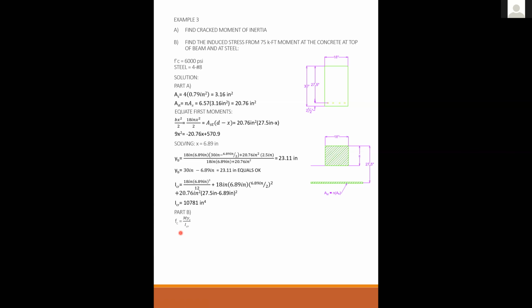So f sub c, the stress in the concrete at the top of the beam, is My over I. So I plug in my 75 kip-feet, convert to inches, times y, which is 6.89, over 10,781, and I get 0.575 KSI in compression. Please note that we solved for the neutral axis as 6.89. It is not 15 inches. It's not to the center of the uncracked section anymore. Once the section has cracked, it fundamentally changed the properties of the whole section. So it is 6.89, not half of 30, okay?